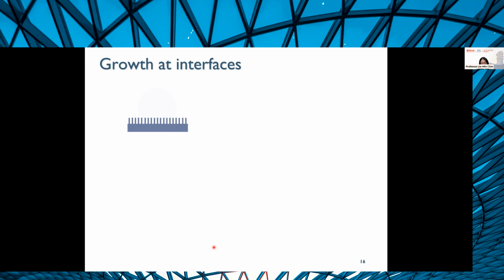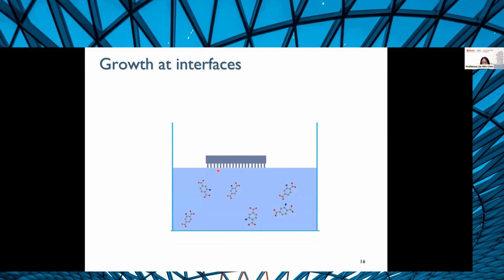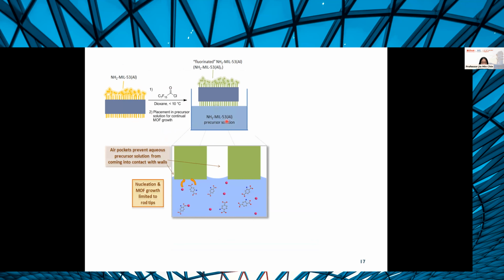What if we just take that and flip it upside down, put it in a beaker of liquid, and let it try to selectively grow a mushroom cap at the interface? And that's what we did. We took these amino MIL-53, functionalized it with fluorination, then stuck it in a precursor solution.